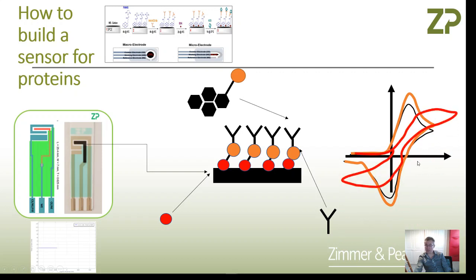And then we characterize the surface. Now the new CV is much more what I would have expected where, in fact, the peak current here has shifted and decreased. So the height has decreased and it's moved to higher potentials. And that's kind of what I would expect because we've basically been blocking the surface. So this first slide really has been about how we would take a screen printed electrode and convert it into an electrode that should be more like a sensor in terms of specificity and selectivity.